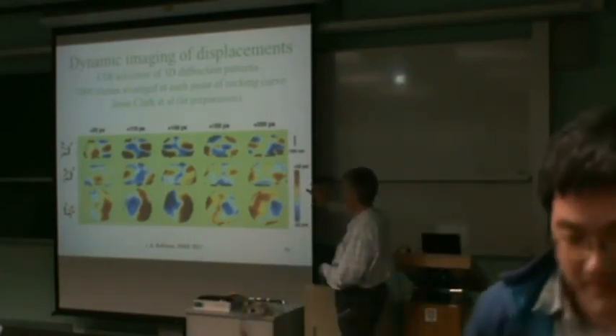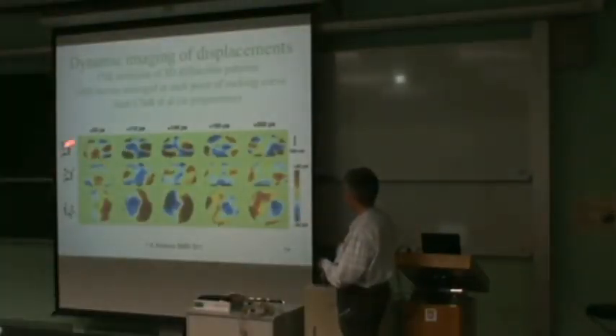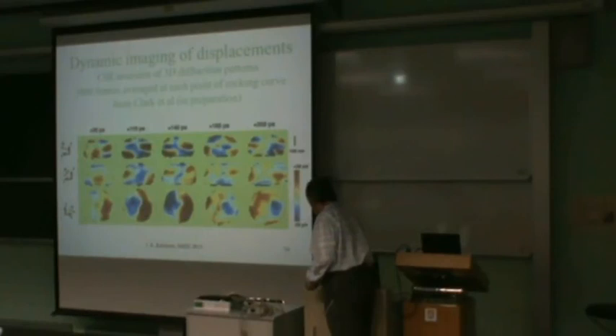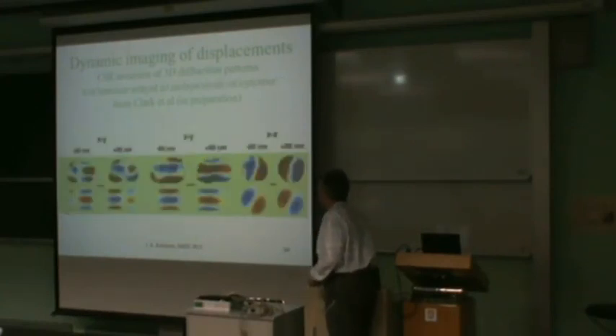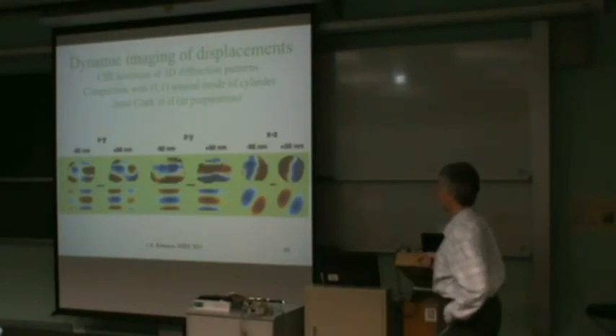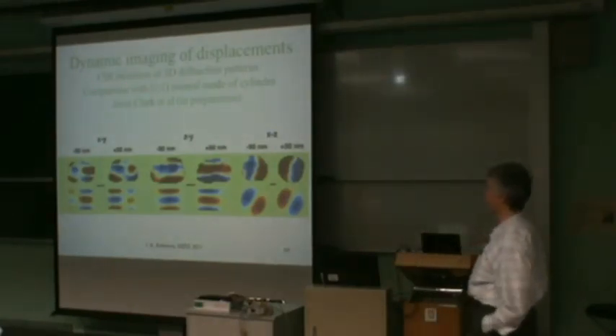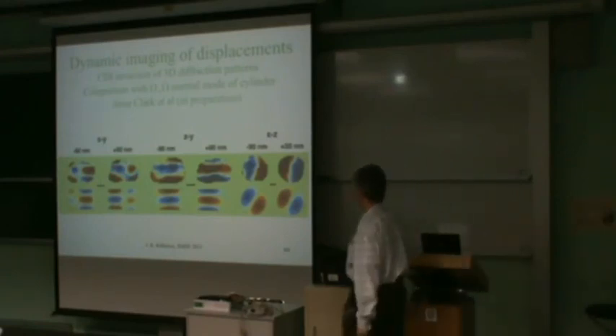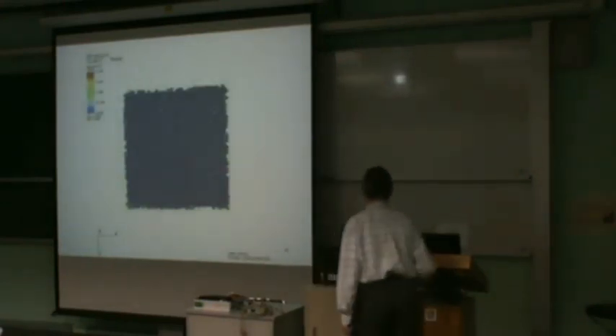We're looking at the vibrations of the crystal measured as a function of delay time after the start of the vibration of the laser. And we get a pretty good qualitative agreement with a higher order shear mode of a cylinder, which is in some notations indicated as the 1-1 normal mode. So we can agree relatively well with the pattern of expansions and contractions with this higher order mode. So this is something that still needs to be tried with semiconductor devices one day. But this is looking into the future.